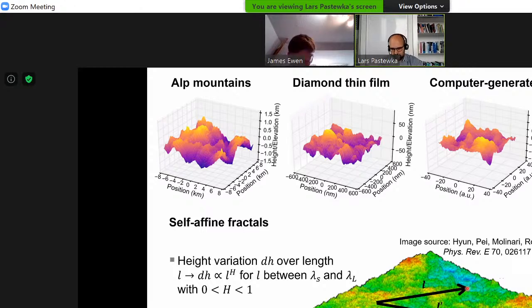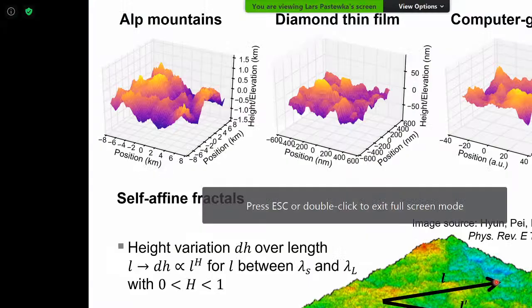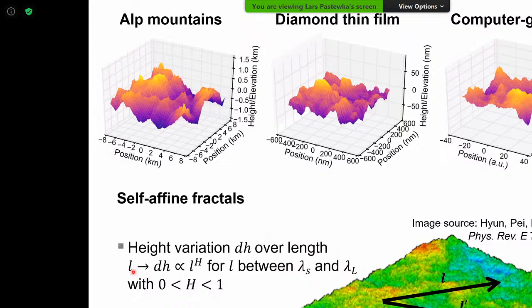So I get, of course, different height distances depending on where the arrow sits. But I can ask the question, what is the amplitude of that height variation at a distance L? And it turns out that for many, many surfaces, or in particular for surfaces that have these self-affine scaling properties, this height variation delta h scales with the distance to some power of capital H, which is called the Hurst exponent, and H is between 0 and 1.